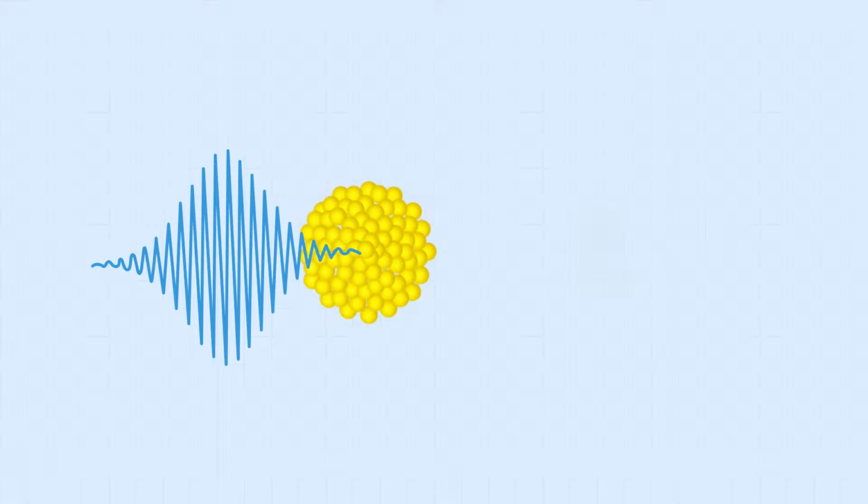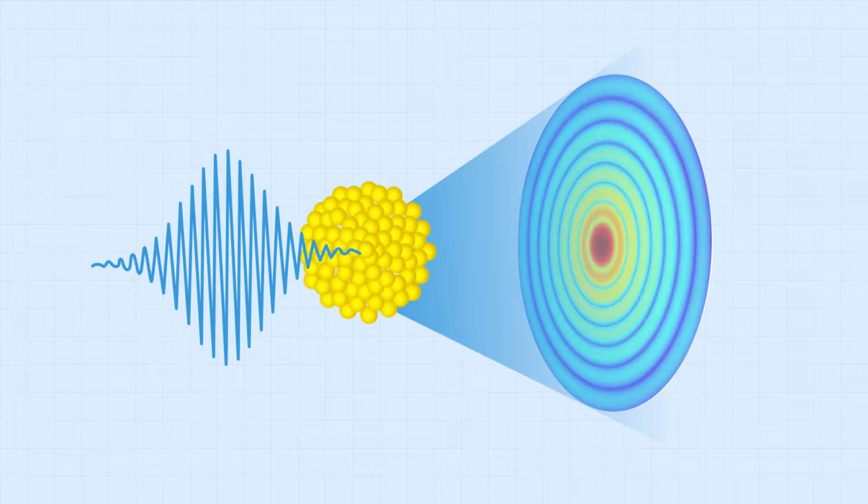With an ultra-short, highly intense X-ray pulse from a free electron laser, a nanoparticle can be imaged by recording the elastically scattered photons in the far field. The resulting diffraction pattern encodes the geometrical information about this particle. However, while irradiating the particle, a nanoplasma is formed and our sample is destroyed, driven apart by Coulombic forces.